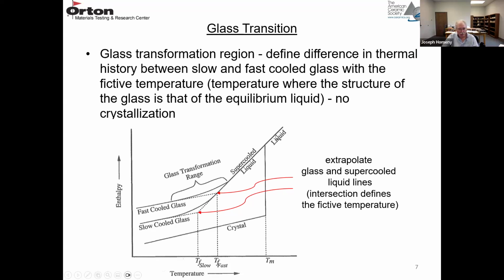So if you extrapolate these curves, the glass and supercooled liquid lines, you end up with that point there. That's the fictive temperature for fast cooling. If you extrapolate that curve and this curve, that's the fictive temperature for slow cooling. So the intersection of those lines defines the fictive temperature. So the slower the cooling rate, the lower the fictive temperature. And again, the fictive temperature is where the structure of the glass is the same as that for the equilibrium liquid. Below the fictive temperature, the glass structure is fixed.